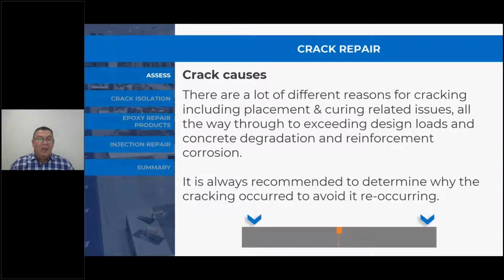For crack causes, there are a lot of different reasons why cracking occurs, including placement and curing related issues in the initial stages, all the way through to exceeding design loads. Concrete degradation or reinforcement corrosion can also cause cracking. So it's important to understand what exactly is going on before you set about repairing a crack. It's always recommended to determine why the crack occurred to avoid it reoccurring. As you'll see here at the bottom, a repair can be undertaken, nicely filling the crack, and if you haven't identified what the reason was, then a crack can occur right alongside the previous crack.